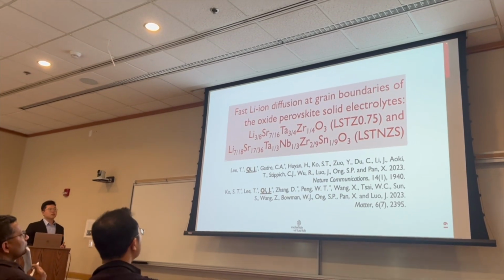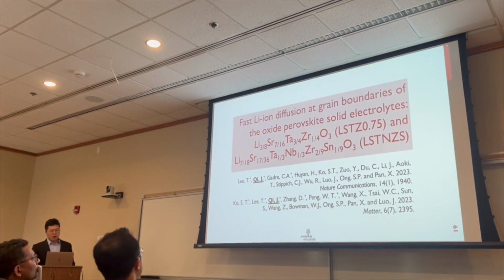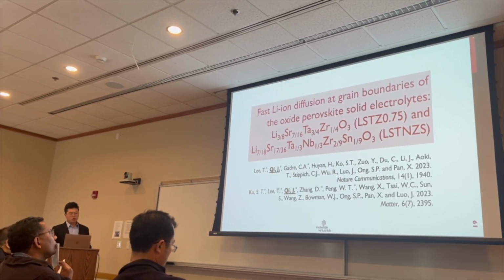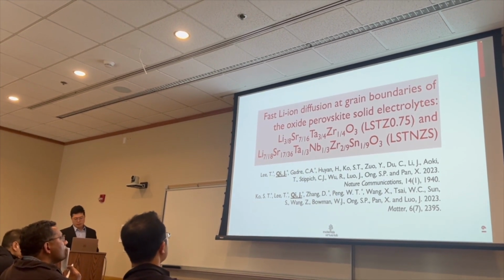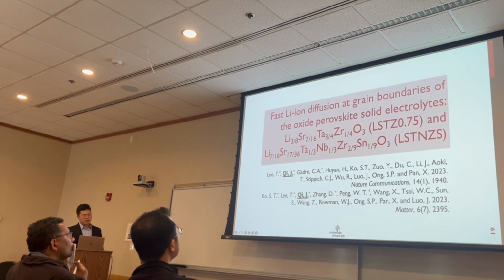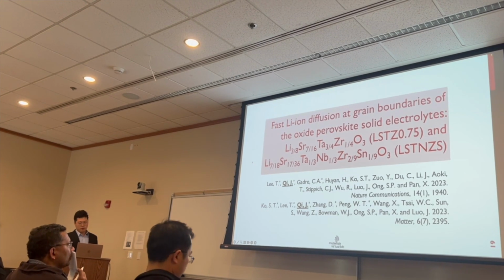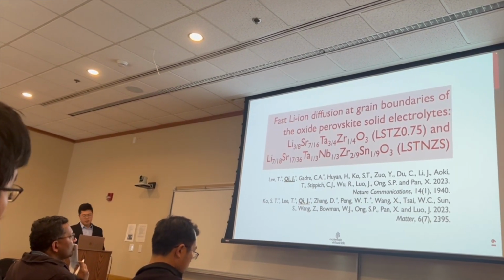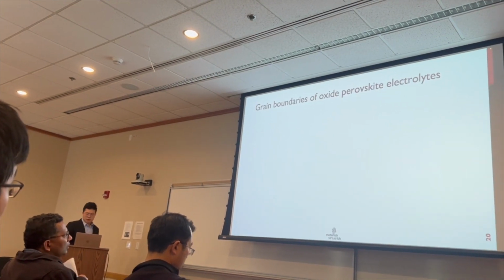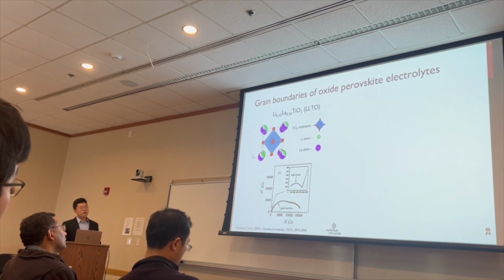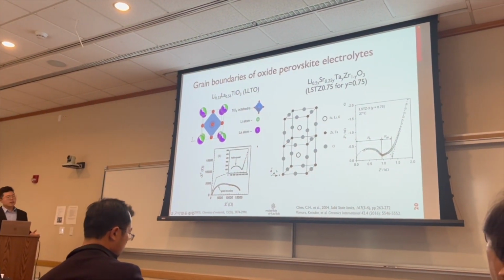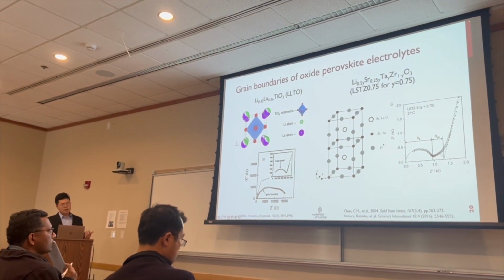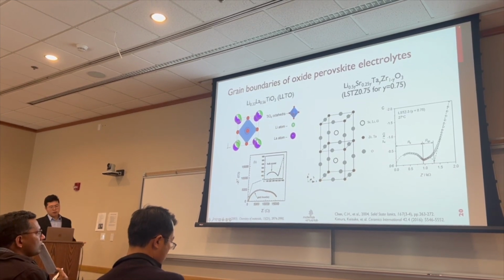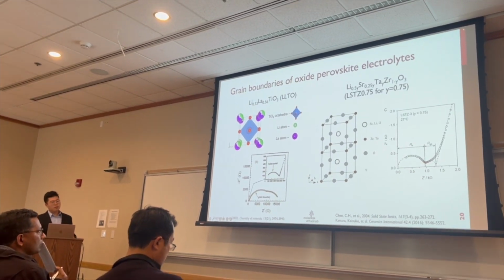That's why we started this project, which is a collaboration with Tom Lee in Xiaoqing Pan's group at UC Irvine, and also Shu Ting Ko from Professor Jian Luo's group at UCSD. This work, we name it fast Li-ion diffusion at grain boundaries of the oxide perovskite solid electrolytes, LSTZ 0.75 and LSTNZS. The reason why we want to study this is that we know LLTO is a superionic conductor. However, its practical application is blocked by its very large grain boundary resistance. The LSTZ family of materials has exactly the same perovskite structure as LLTO. Interestingly, for this material, the grain boundary resistance is low, so the overall ionic conductivity is higher than LLTO, making it a more promising solid electrolyte.